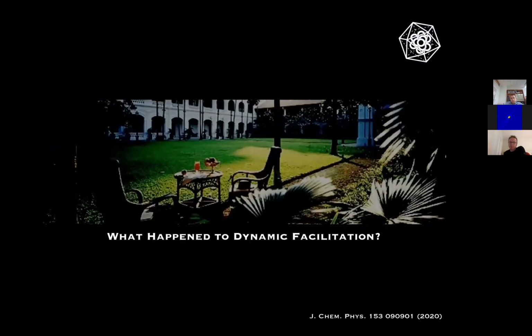Okay, so that started to look like it was rather good for the thermodynamic interpretation for the glass transition. We've shown a change in structure, and we've shown that this change in structure is correlated with the drop in configurational entropy, and we've shown that there is a drop in configurational entropy. So in the remainder of the talk, what I'd like to do is tell you about dynamic facilitation.